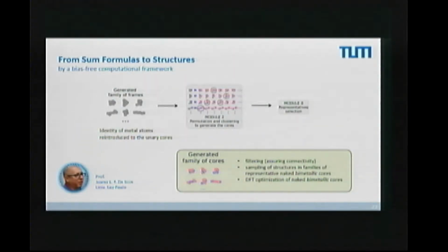Okay, so this can be done in a 3-step process. First, you generate classes of aggregates where you do not take into account the difference of the different metals. And this can be grouped into classes by some clever techniques. I'm not going into detail. Then once you have that level done, you can put in the differentiation of the two different metals, and then you have lots of permutations of the positions. Again, you have to be very efficient, and this is why the computer science comes into play. Once you have done this with a reduced configuration space, the last step is putting on the ligands, again randomly putting them in the system and minimizing it.